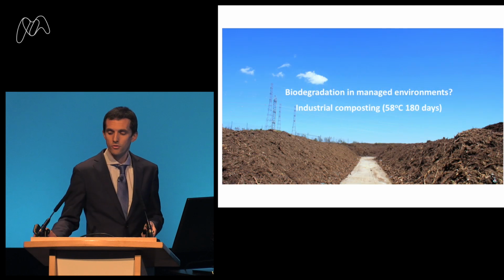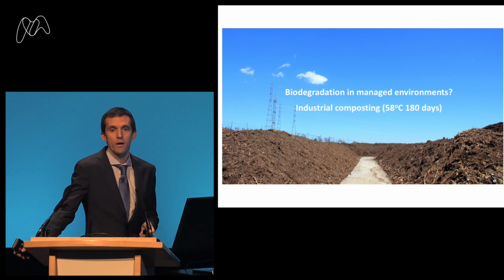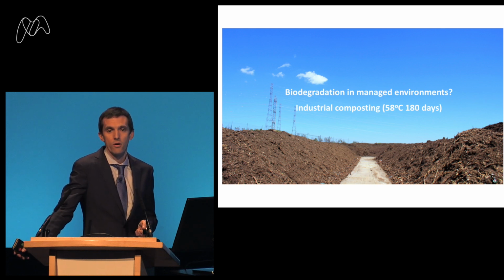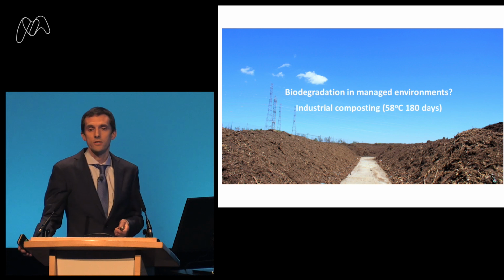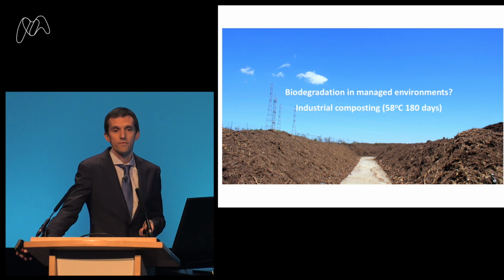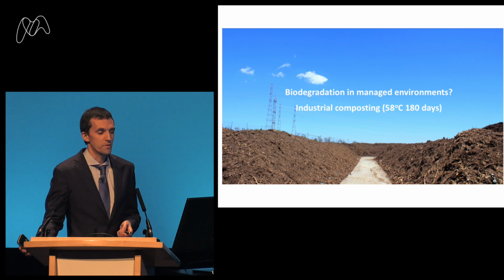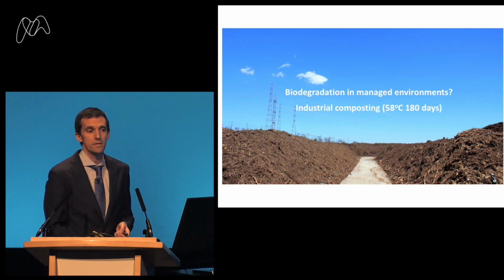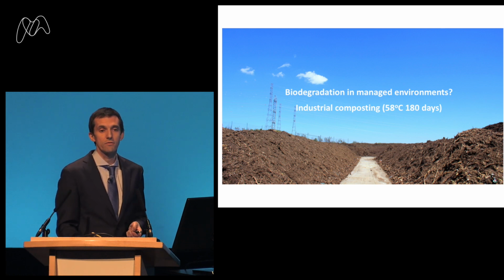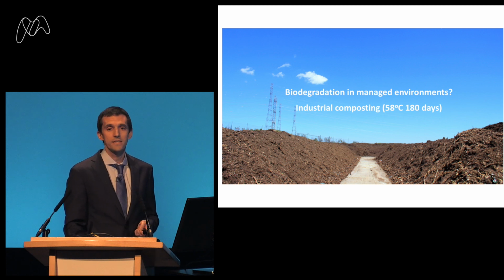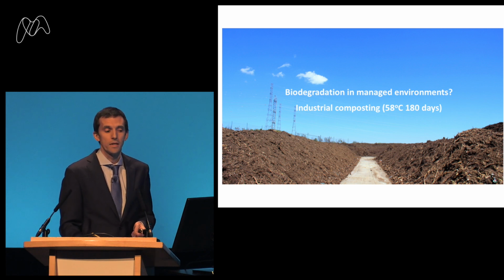So what we decided to do is look at these biodegradable polymers, whether they be bio-based or petrochemical-based, and ask the question, how do they degrade in a variety of different environments? And we split that into managed environments and unmanaged environments. So the first managed environment we looked at was industrial composting. Industrial composting maintains a temperature of around 58 degrees centigrade. And in order to meet the standard of compostability, it must degrade within 180 days, and it must achieve 90% degradation relative to cellulose.